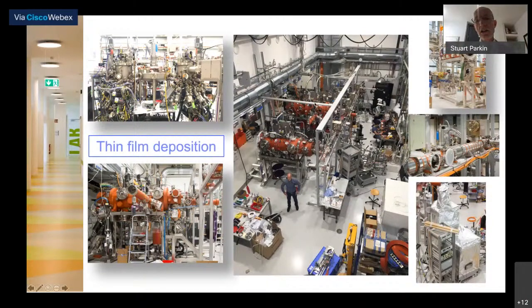But these sputtering systems are connected to a system here shown in the top left, which is 2 molecular beam epitaxy chambers, one designed for oxides, one for nitrides. And these systems also are connected to this ultra-high vacuum tube. So we can build on the same substrate using molecular beam epitaxy, using magnetron or ion beam sputtering. And also we have a pulsed laser deposition, which is not shown in this photograph, but which is now installed in the laboratory. And all of these systems are connected also to a photoemission system for looking at electronic structure in situ. And we've also connected it to a dry box where we can exfoliate materials.